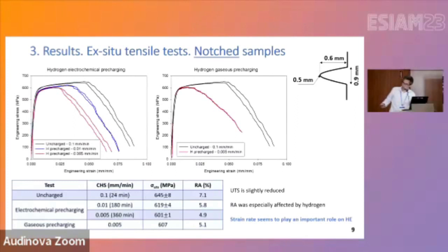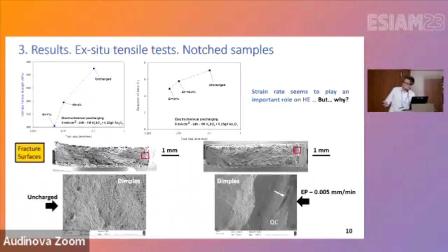And here we can see also that strain rate seems to play an important role on the embrittlement process, despite the low hydrogen diffusivity, 10^-16 meters squared per second, obtained in this steel by means of the hydrogen desorption curve analysis. So according to this, here we have represented the ultimate tensile strength and the reduction of area as a function of the strain rate. Here we can see the embrittlement indexes obtained for the different cases. The embrittlement index indicates the drop in terms of the mechanical property.